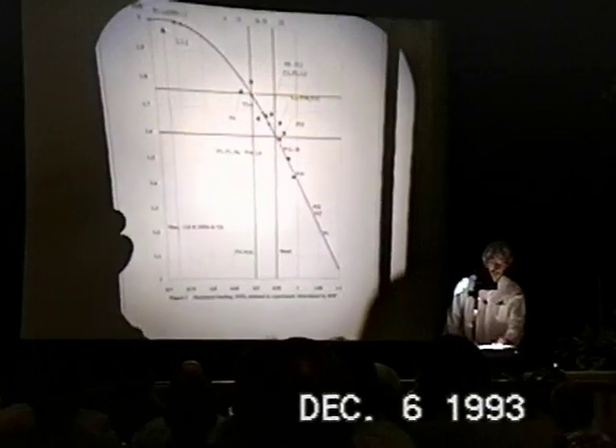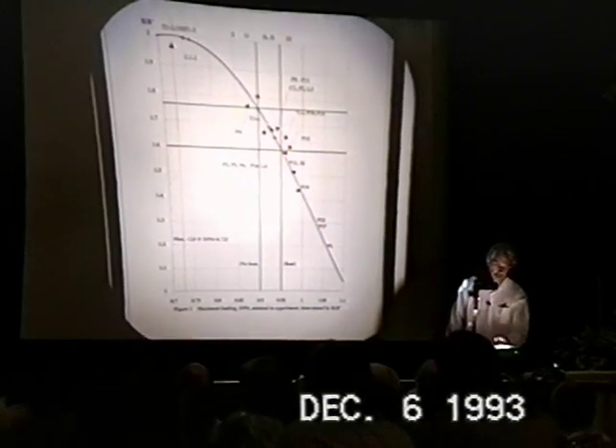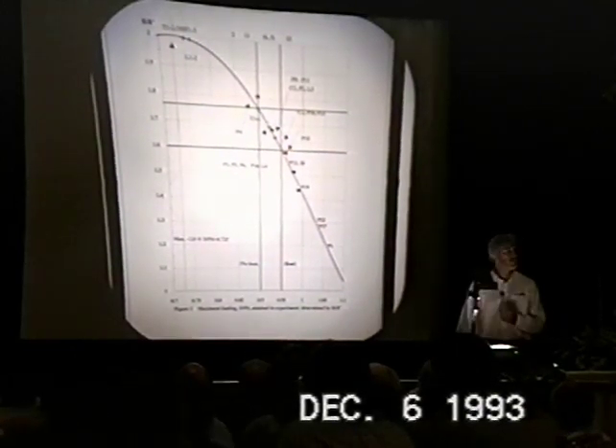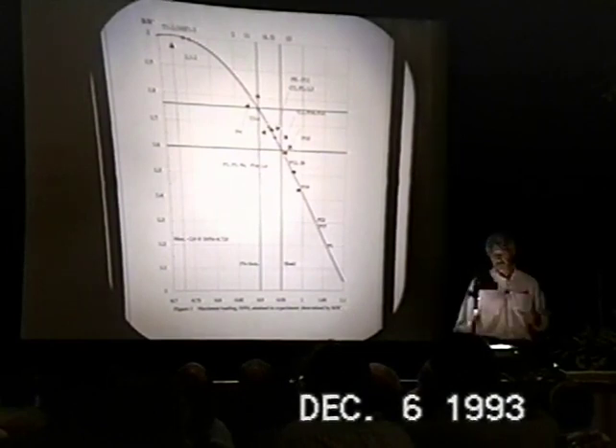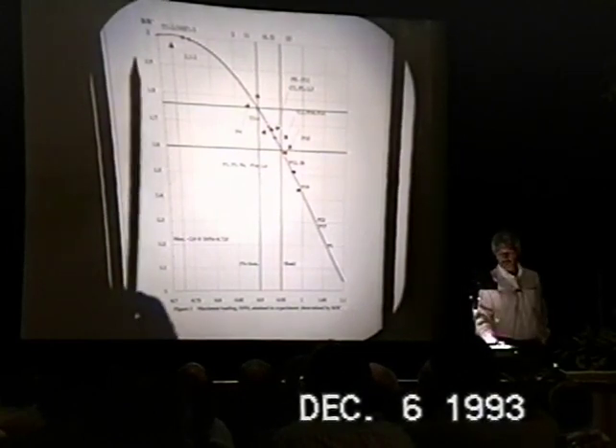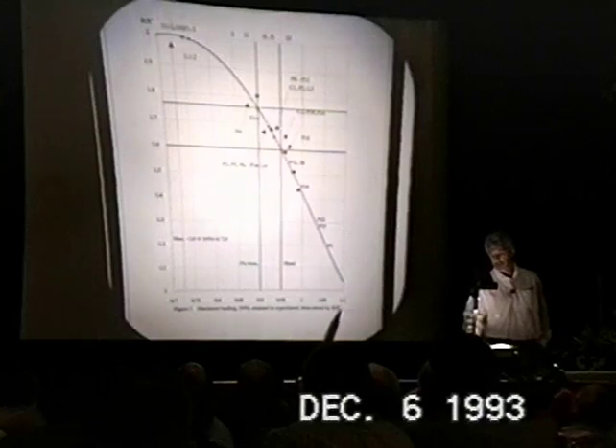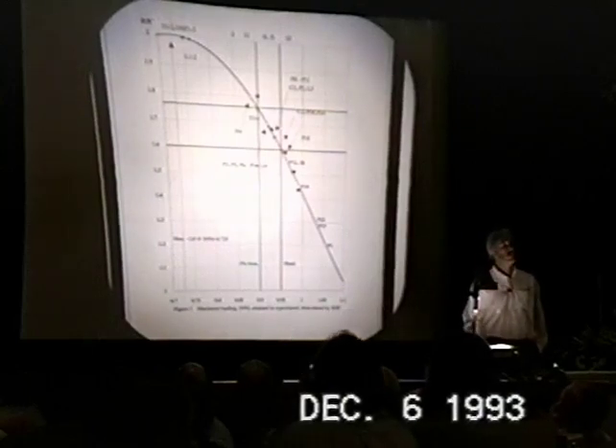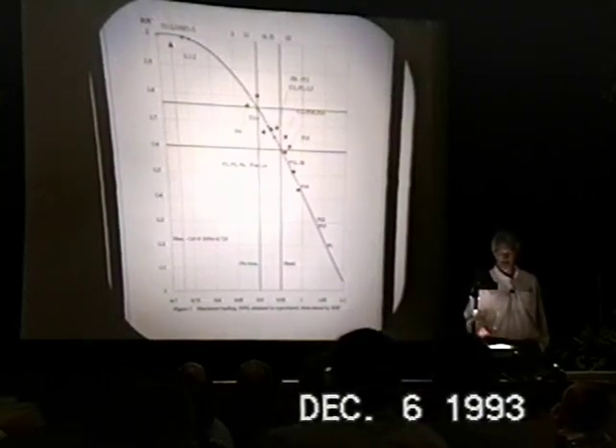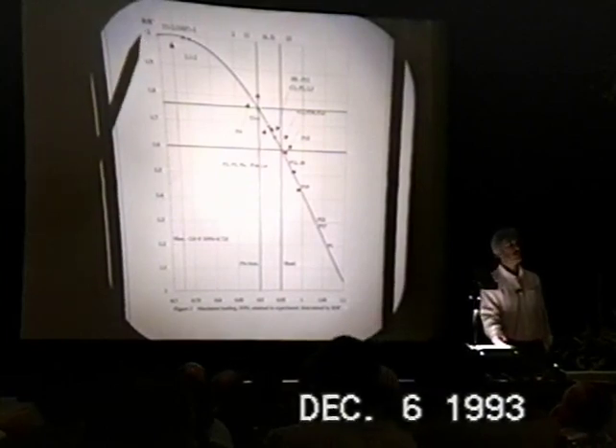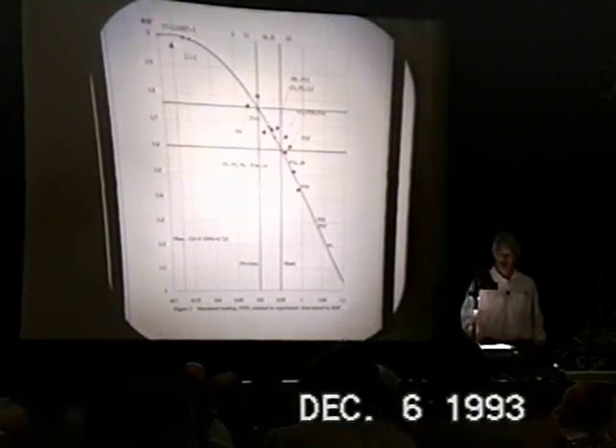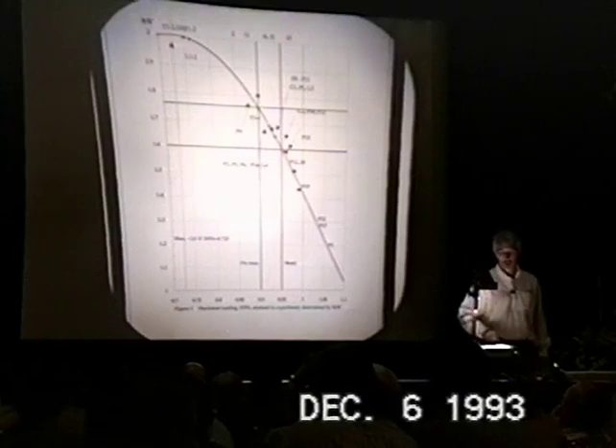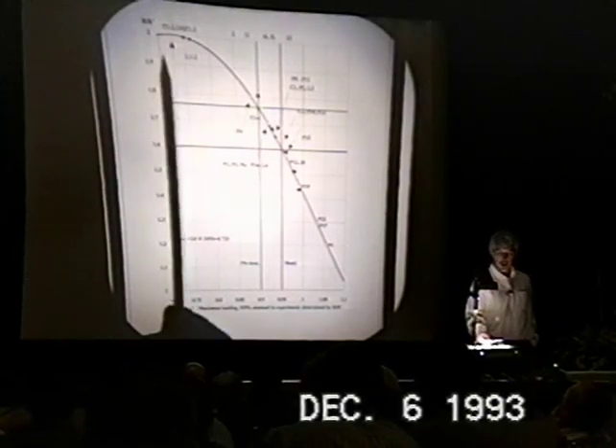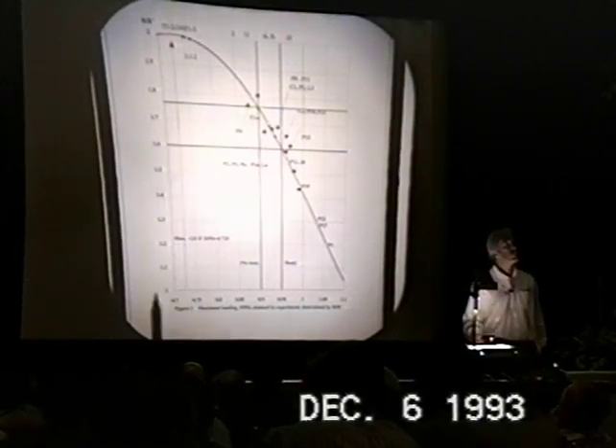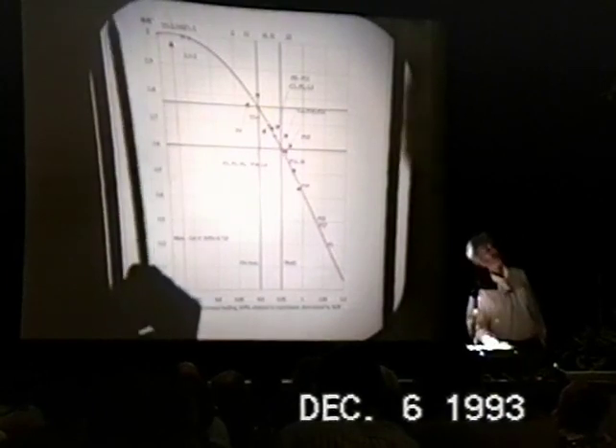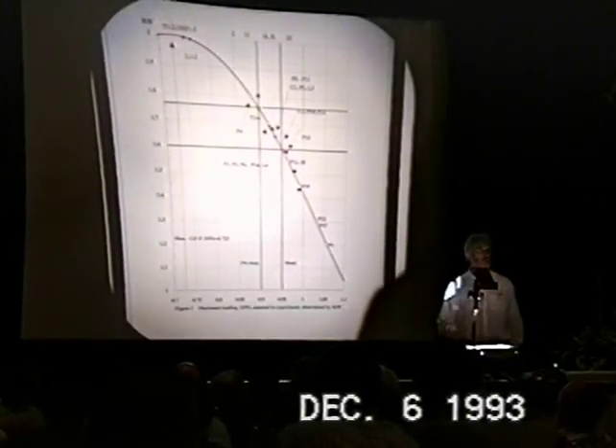Just to remind you why we care about the loading, this is an augmented slide of something that I presented before. This is the resistance ratio versus loading curve for deuterium in palladium. The resistance ratio, of course, is defined to start at 1 at a loading of 0. It goes through a maximum of about 2 at a loading of about 0.725. Then it comes back down the right-hand side.